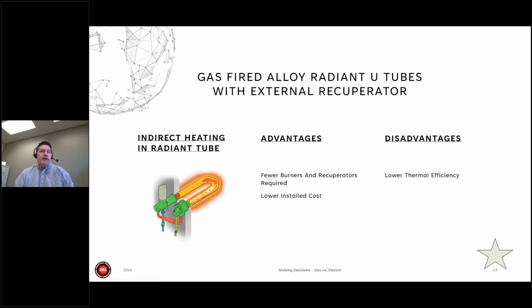Here's an example of an alloy radiant tube, which has indirect heating. The U-tube is one of the more common types of radiant tubes that are installed in furnaces. The setup is that you have a burner going down one of the legs of the U, and the exhaust is coming out the other leg, where then you would have a recuperator that heats up the air, and preheat air is then put into the burner to increase efficiencies.